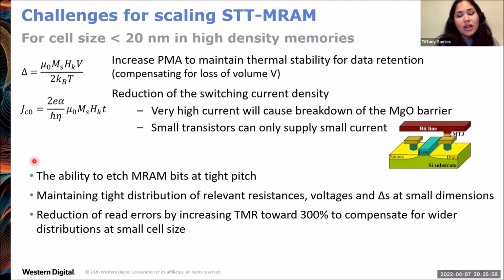Another major challenge is on the fabrication side. How do you etch MRAM bits at the tight pitch that's needed for high density, and how do you do that while maintaining tight distributions of your various performance parameters? Another challenge is if you make lots of small bits, your distributions are going to go up for these small cell sizes, and you need to compensate for that by boosting your read signal. So then TMR needs to be upward toward 300%.